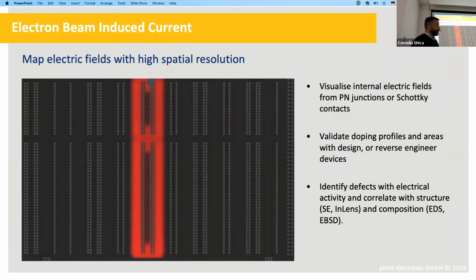This is an example where you can map where the electric field is. We have some high power transistors. In the SE imaging grade, we don't see the fields. We can only see the plugs that connect our junction to the rest of the circuitry. And once we use EBIC, then we can illuminate, and we actually overlay this red over the SE image, and we can see where the field is. If you do device research, you can then go, is it where I meant it to be? Is it bigger? Is it smaller? You can interact with it. You can apply a bias. You can go to reverse bias and make it larger. You can go into forward bias and make it smaller.